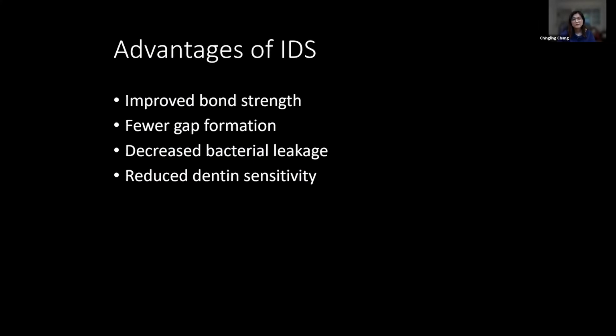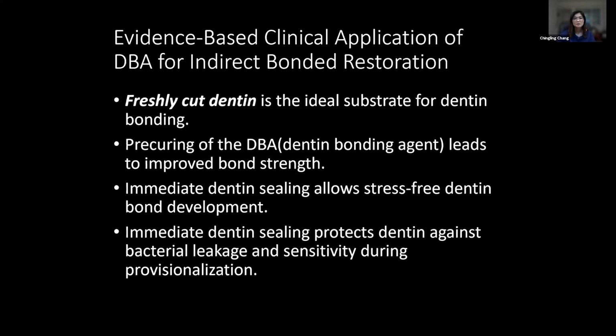The advantage of immediate dentin sealing is we can improve the bond strength, and we have fewer gap formations on the tooth surface. And after we seal the dentin, we decrease the bacterial leakage, and we can also reduce the dentin sensitivity. There is a lot of evidence that shows the advantage of dentin bonding agent in immediate dentin sealing.